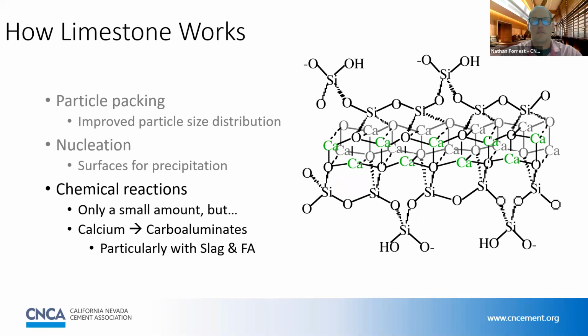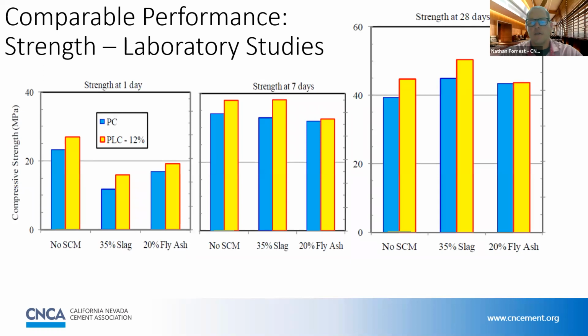And now we'll talk a little bit about strength and durability. Now what we have here is strength gain at 1 day, 7 days, and 28 days using both ordinary Portland cement in blue and Portland limestone cement in yellow at 12% limestone. We're also looking at 3 different cementitious packages. On the far left, we have no supplementary cementitious materials. In the middle, we have a 35% slag replacement. And on the right, we have a 20% fly ash replacement. And what you see is that in all cases, at all ages, and in all cementitious packages, the performance of the Portland limestone cement is comparable to that of ordinary Portland cement.